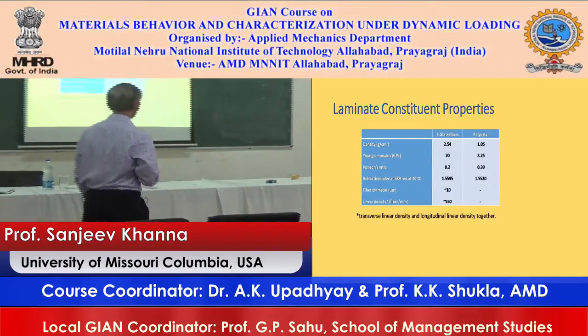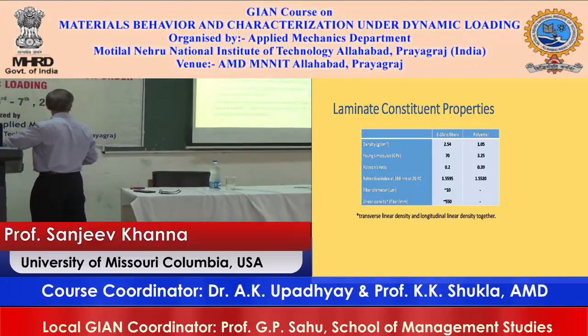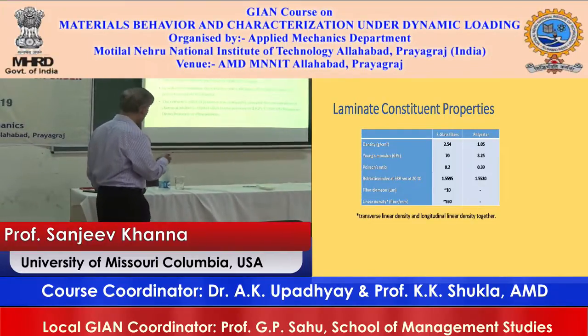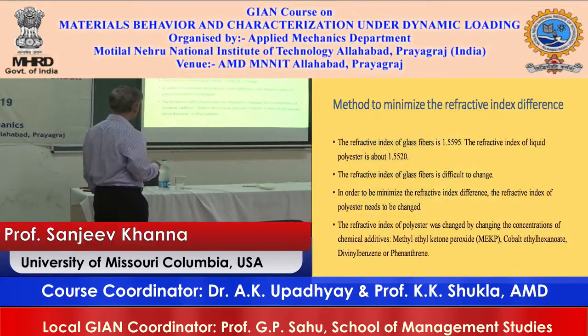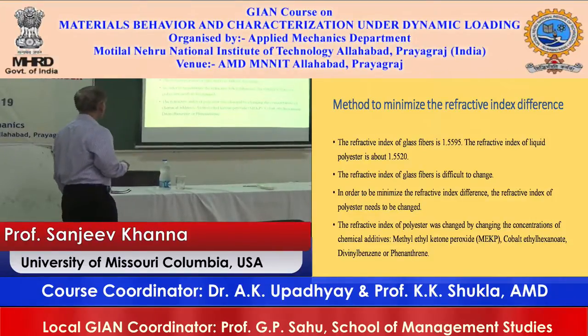Okay. So that's what we try to chemically match. And as I said earlier, the refractive index of glass fiber is very difficult to change. People have tried that. So what we did was we changed the refractive index of the polyester, the matrix itself. Now